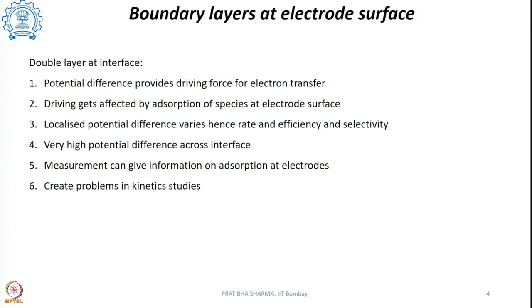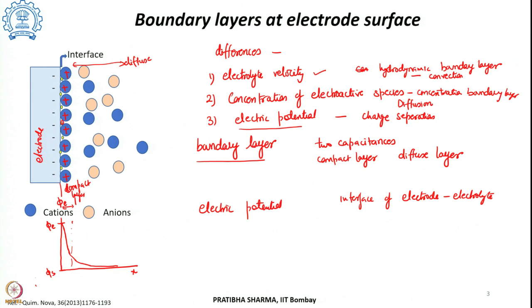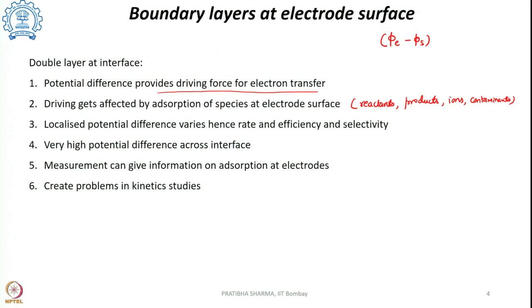Now, when this difference in the potential, phi E minus phi S, exists, that double layer at the interface has several consequences. This potential difference provides the required driving force for the electron to transfer across the electrodes, and that driving force however gets affected because of the adsorption of different species at the electrode surface. These could be the reactants, the products, the different ions, or the contaminants involved in the process. Like in the earlier figure, we have shown the solvent molecules which get adsorbed onto the electrode surface, and that changes this potential difference in the process.